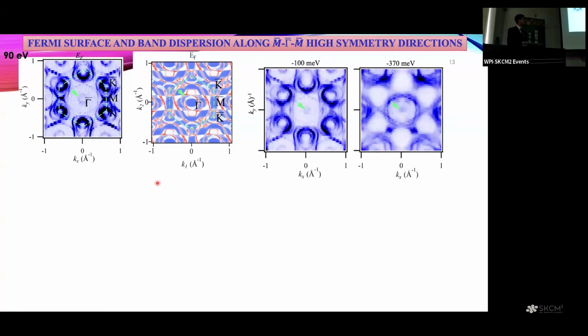And then we did DFT calculations in collaboration, and even though it looks complicated because you also have surface and bulk together, in general, the agreement is okay. Because ytterbium has 4f states and DFT doesn't work well with 4f states, in our calculations, the ytterbium 4f states are frozen. So we have used a high value of U to keep the 4f states away from the Fermi level.